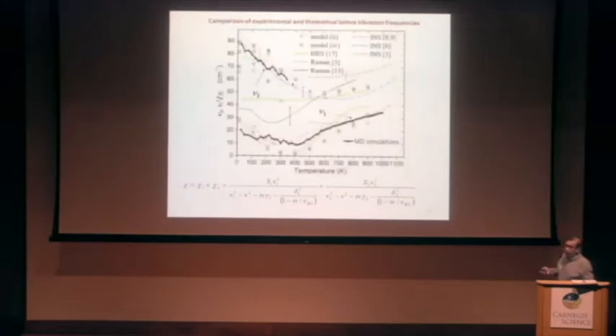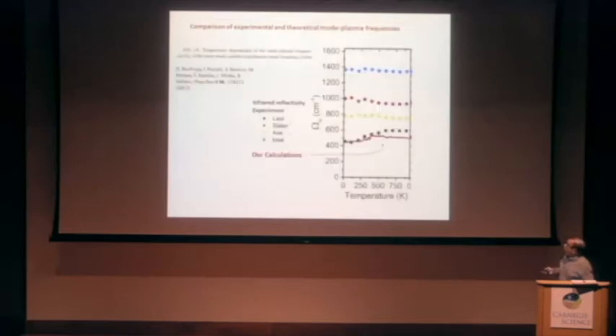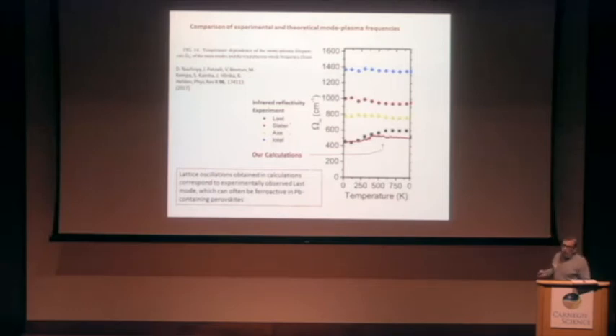And now, if we compare our results, which are shown by the solid black line with triangles, with experiment, we can see that in experiment we can find, in any temperature and frequency range, good correspondence. I will talk about this a little bit later. What is important, this is the mode plasma frequency which we calculated for our low-lying mode, and our calculations fit very well to the experimental data found for the last mode, which is known to be often ferroelectrically active in lead-containing perovskites. Thus, we simulate in practice the lattice mode, and this is the soft mode. I will show it later.